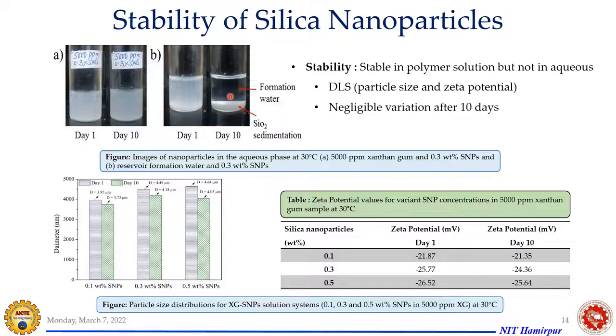Why? Because for these nanoparticles the electrostatic attraction is more, so the particles come closer, form agglomerates, and then settle at the bottom. Whereas when you have these nanoparticles in the polymer solution, you can see even after 10 days, these particles are stable. If you extend it to certain months also, we expect it to be stable. Why? Because when you inject these nanoparticles in a polymer solution, the polymer keeps the nanoparticles in suspension. The polymer chain is there, and the nanoparticle is attached to the polymer chain. Because of this, the electrostatic repulsion force is pretty high compared to the other case. This keeps the nanoparticles in suspension. It will not allow the nanoparticles to come closer, agglomerate, and settle down, which we have seen in the case of only water, that is formation water flooding.